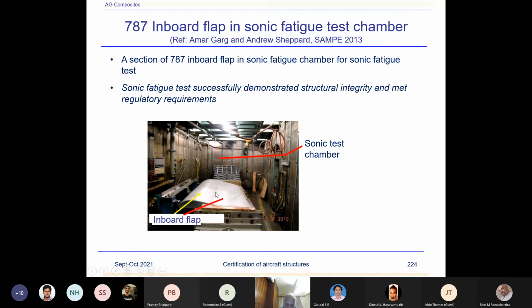So this one, as you can see, is the inboard flap of the 787. And this was again done in Seattle. In Melbourne, we don't have this testing facility for sonic. We made it over here and it was provided for testing in Seattle. So you can see the sonic test chamber. It was put in the chamber, and then depending upon the spectrum, we had to test for a particular overall sound pressure level, and then show, using the analysis also, that it simulated similar modal distribution, modes of vibration, as the test indicated.